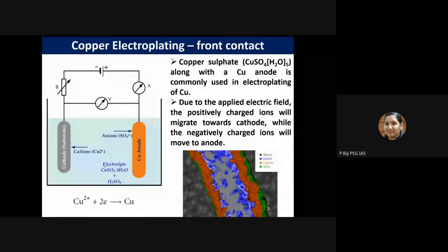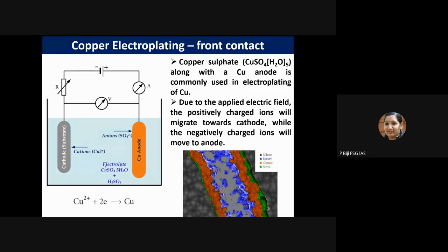In this case, copper sulfate along with a copper anode is commonly used for electroplating of copper. You need to apply some electric field. Due to the applied electric field, the positively charged ions will migrate towards the cathode, while negatively charged ions will move towards the anode. You know that the reduction happens at the cathode side, and the cathode side is your wafer. So you will have the deposition of copper on the surface of the nickel, because other sides are masked by the photoresist. The deposition happens only on the patterned lines, and copper will be reduced into metallic copper.